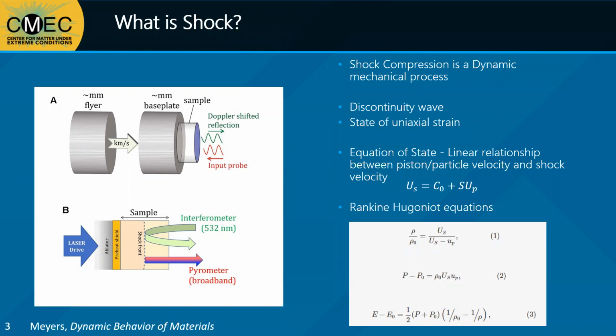This laser heated material is then propelled away at a high velocity, causing the remaining material to accelerate inwards. This method is the same as how some rocket propulsion works. In solids, this one-dimensional loading and inertial confinement results in a state of uniaxial strain. Shock waves travel faster than the sound speed of the material, with a shock velocity that is dependent on the amplitude of the wave. Shock wave behavior in a material can be compared to how a snowplow operates.